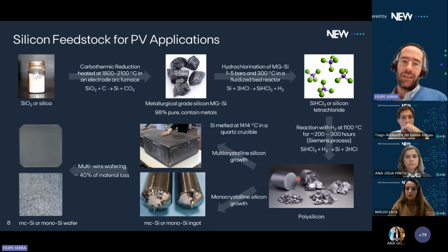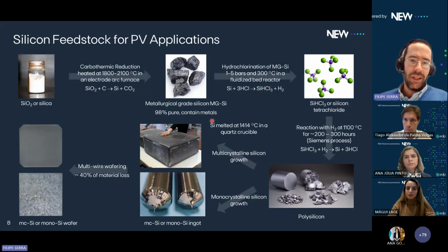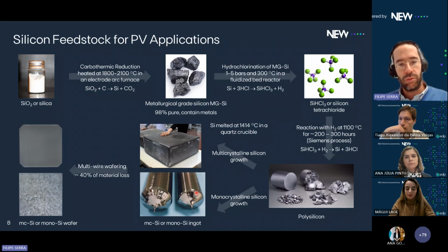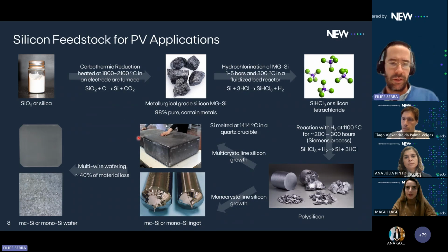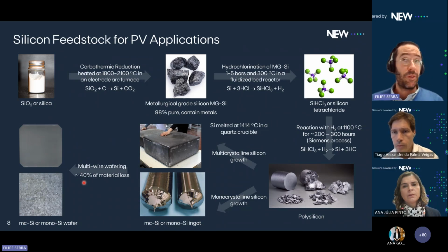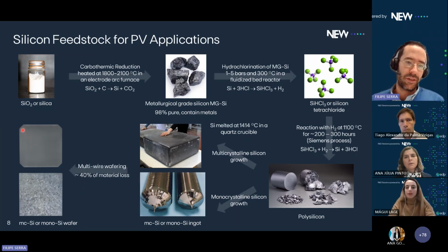This material, polysilicon, is 99.9999999% pure. With that material, we then melt it in quartz crucibles in order to obtain either a multicrystalline silicon growth, which are these big slabs after solidification of that melted material, or we can also grow these cylindrical ingots to obtain monocrystalline silicon ingots. After that, we have this recrystallized silicon material, which is almost pure, and we then have to do wafering using multi-wire cutting, and 40% of that material is wasted, and we obtain this. This is a monocrystalline silicon wafer, and this is a multicrystalline silicon wafer that then is put in the assembly line for making solar cells.